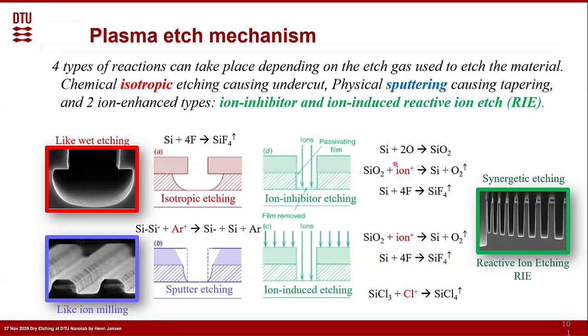Then we have the second type, which I can first also show. It's called ion induced, with the silicon oxide. But now we are not etching silicon, but we are going to etch silicon oxide. And in this case, still the ion will remove the oxygen by knocking it out. And here, again, let's say the silicon, which is then coming available, will be removed by the fluorine into silicon tetrafluoride. But in this case, all the time, we really need the ion to crack every single oxygen molecule from the silicon oxide lattice. That means that the etch rate here is much more solely controlled by the ion density.